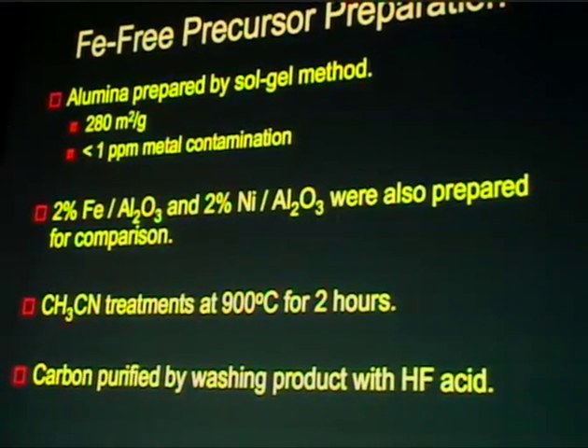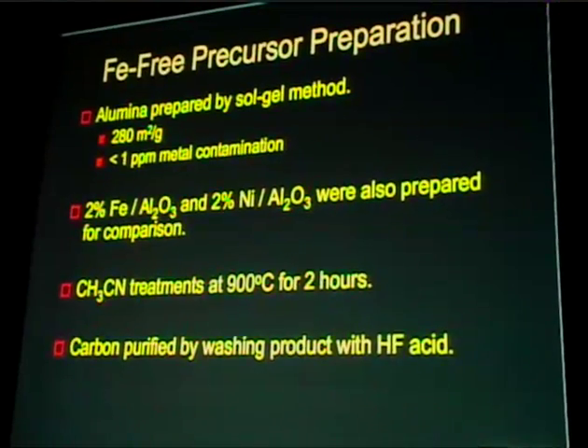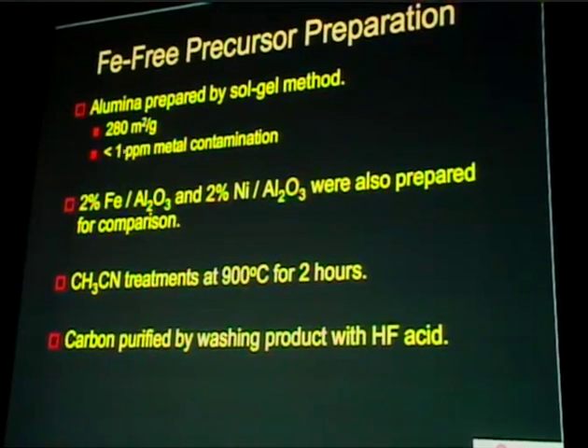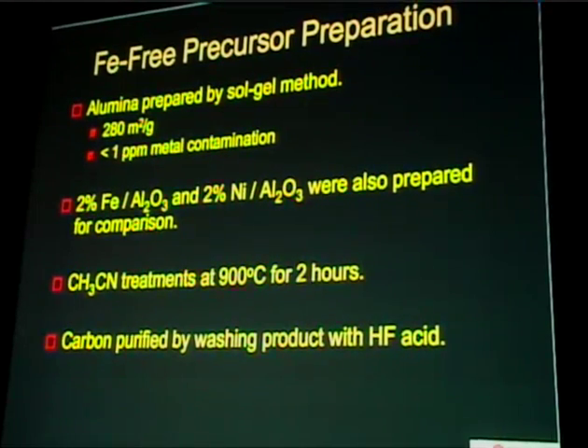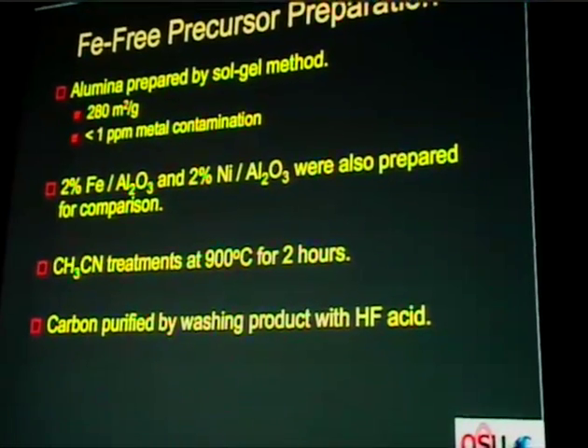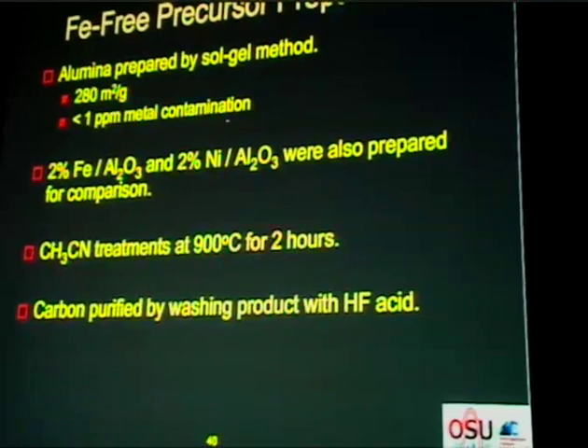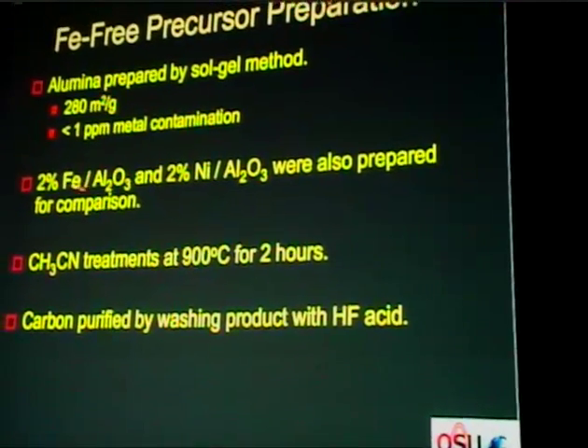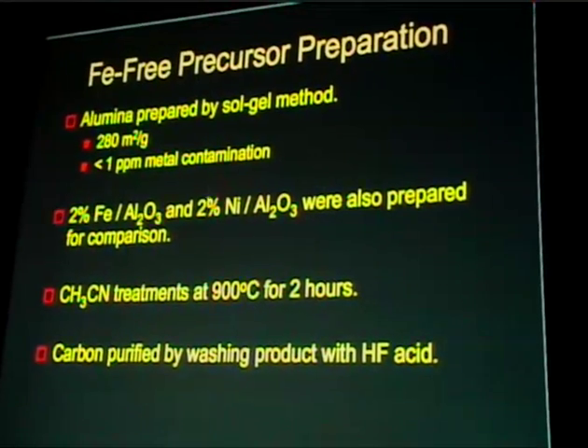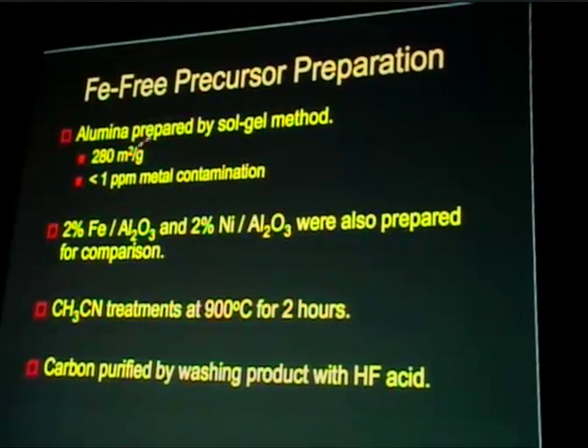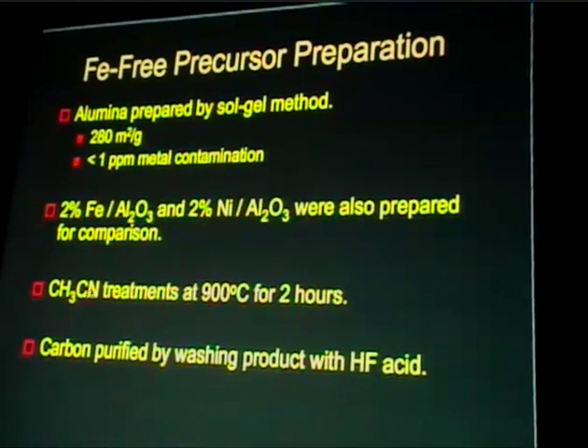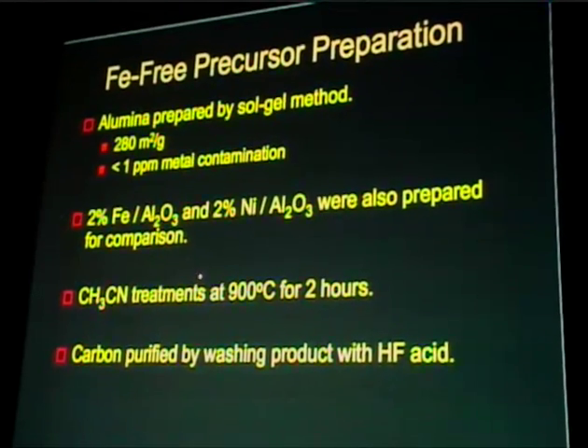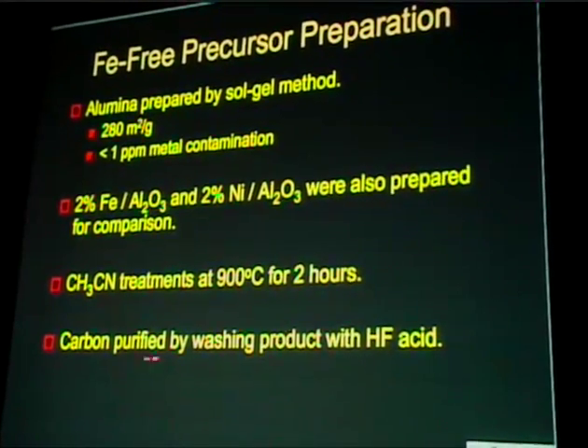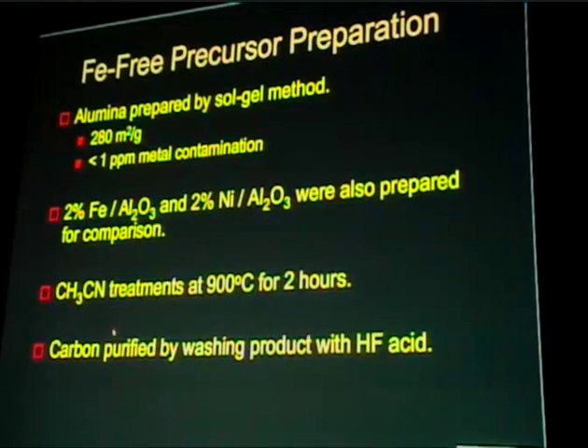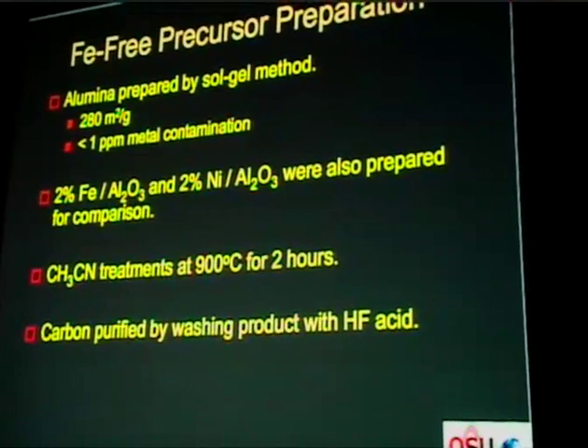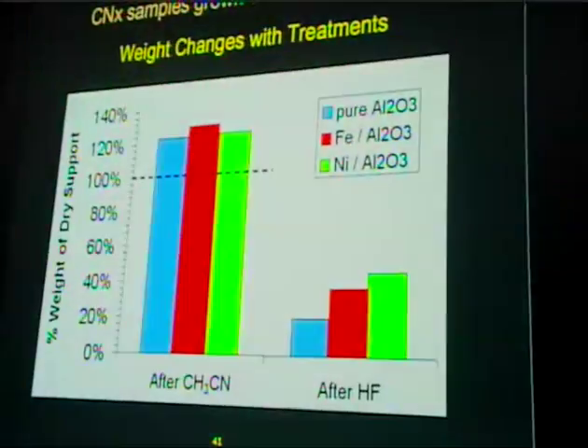And we prepared some alumina support using a sol gel technique with very, very low metal contamination and essentially no iron contamination. Also, for comparison, we prepared some supports with iron doping or nickel doping. And then we took these materials through the same acetonitrile pyrolysis treatment, and then we purified these materials. We purified the carbon by washing the product with hydrofluoric acid.